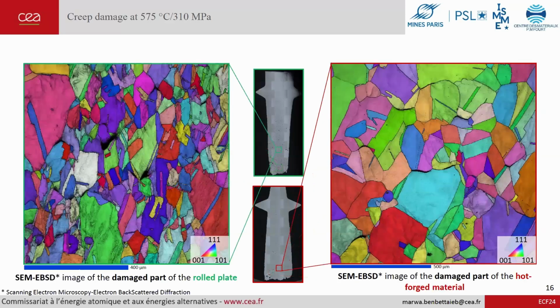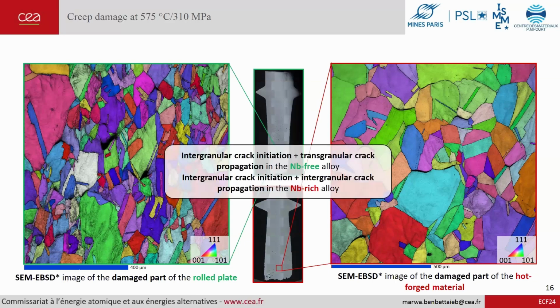So that's why I'm showing here EBSD maps for the two alloys. The map on the right just confirms what I've said for the hot forged material. And on the left, we can see that the cracks also are intergranular, but the propagation of our cracks is transgranular.